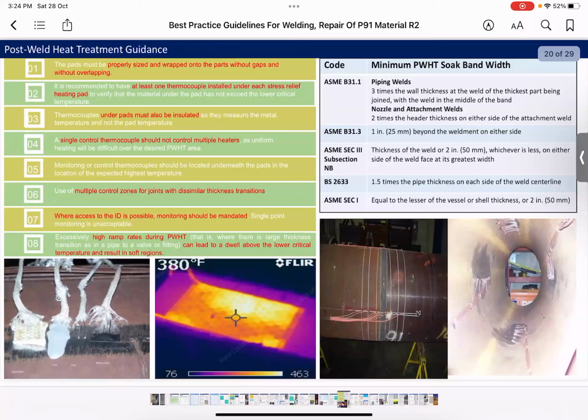This is very important when you have dissimilar thickness between the two sides of the weld. We should have multiple thermocouples for controlling or monitoring the temperature there. And the thermocouple location should be from OD as well as ID. The soak band, the heat band, the thermal gradient band should be calculated, marked at site, and witnessed. This is very important for any inspector or inspection engineer involved in P91. These steps are very important to be witnessed.